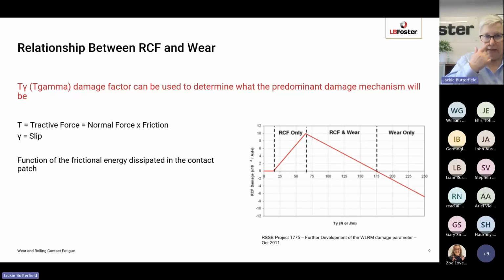Another way of looking at rolling contact fatigue and actually predicting it is to use a T-gamma damage factor, which is a calculated factor based on vehicle dynamics and also the wheel-rail interaction. So you can actually predict what the predominant damage mechanism will be.